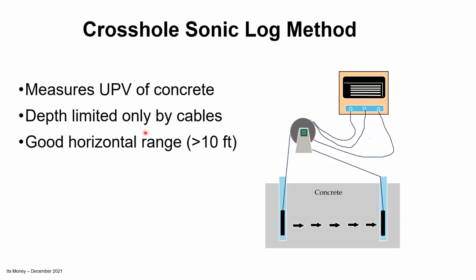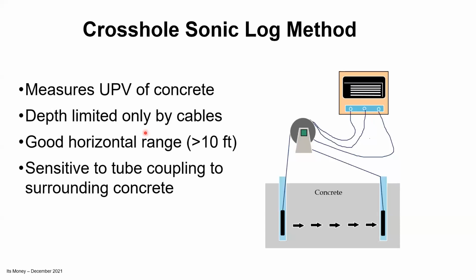It has a good horizontal range, more than 10 feet for most modern equipment, so it can be used to assess things like slurry walls and secant wall structures. It is, however, sensitive to the tube coupling to the surrounding concrete, which in the case of existing foundations isn't a problem because you're probably going to be working in core holes.